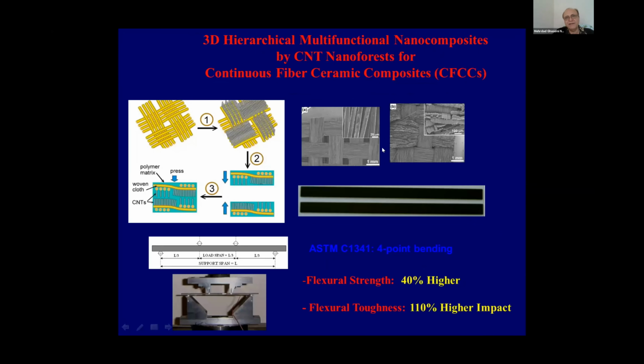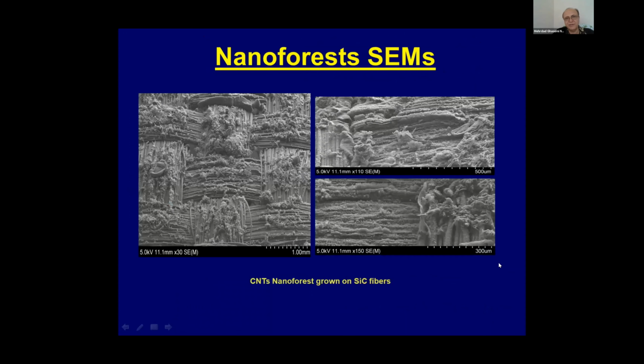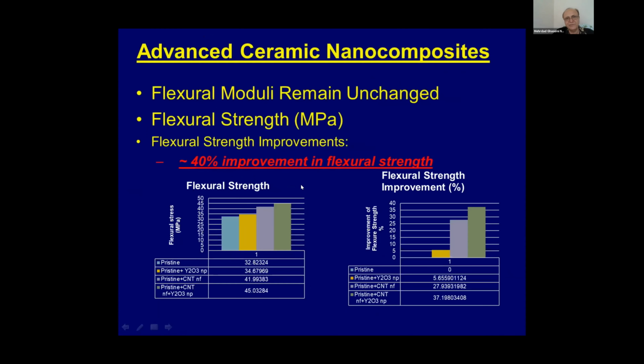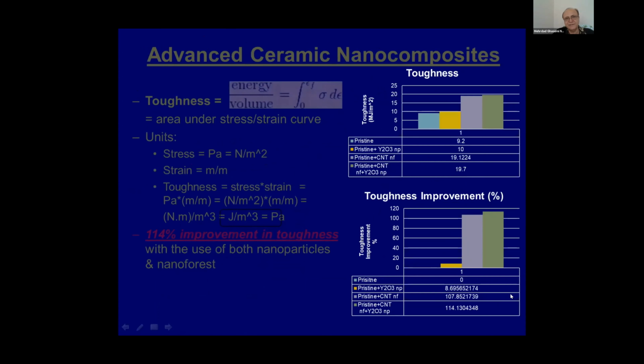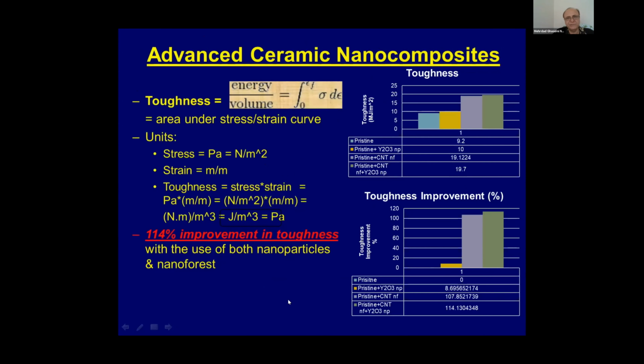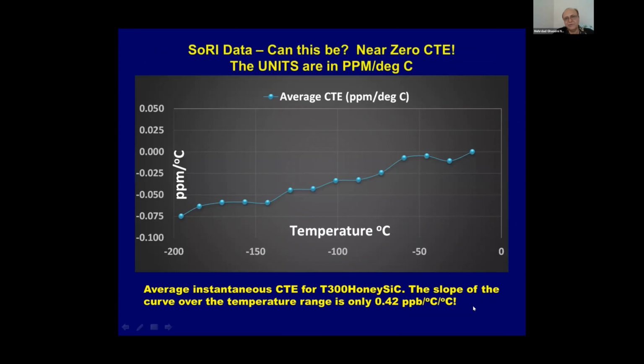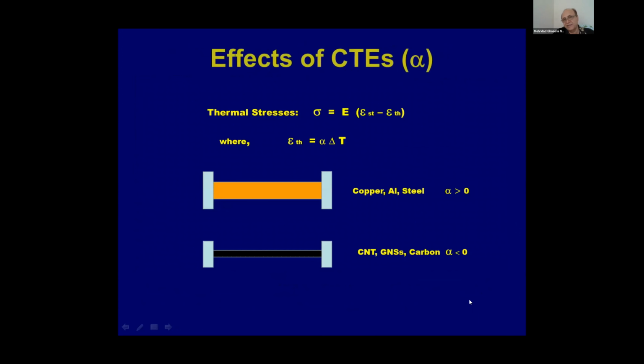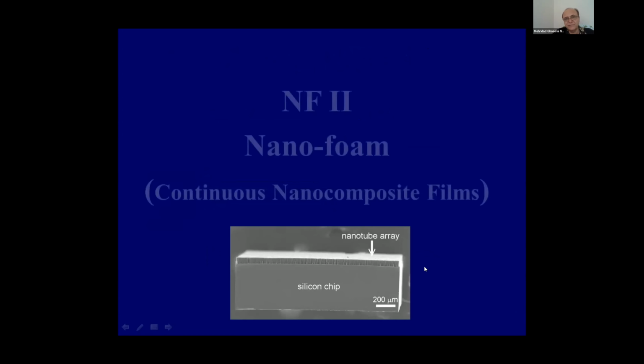So we applied that also to ceramics. Also in ceramics, we get 40% improvement in flexure strength and 110% improvement in toughness for a ceramic composite. These are ceramics. So as I mentioned, 40% improvement in flexure and 114% improvement in toughness. Also, they have a close to zero coefficient of thermal expansion that has application in space. So I showed, for example, regular materials, copper, aluminum, steel, they have positive coefficient of thermal expansion, CNT, GNS, they have negative coefficient of thermal expansion.